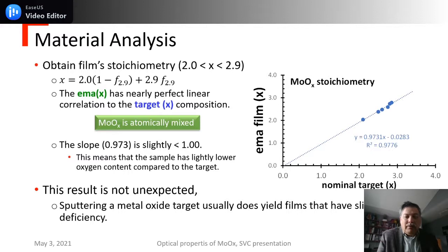Well, when we do that, we find that the stoichiometry of the film is slightly different from the stoichiometry of the target. Look at this slope, 0.973. It is slightly less than a slope of 1. 1 would be a one-to-one correlation, but it's slightly less. And what this means is that the film is slightly oxygen deficient in comparison to the target's stoichiometry. This is quite expected. Films never have the same stoichiometry as the target, and oxygen is usually lost slightly due to pumping from the system. So oxygen is usually a little bit deficient.